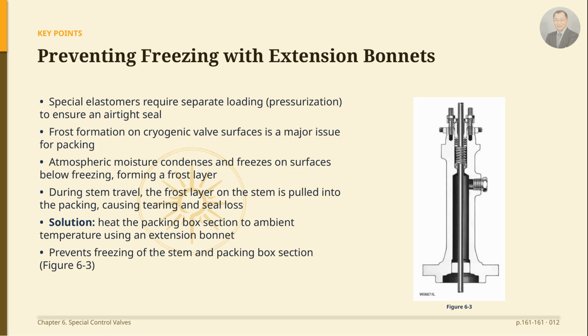Packing becomes an issue in cryogenic applications because of the frost that forms on the valves. Moisture from the atmosphere condenses on colder surfaces, and if the surface temperature is below freezing, that moisture freezes into a layer of frost. When this frost and ice form on the bonnet and stem areas of control valves and the actuator strokes the stem, the frost layer on the stem is drawn into the packing, tearing it and resulting in a loss of seal. The solution is to use extension bonnets.